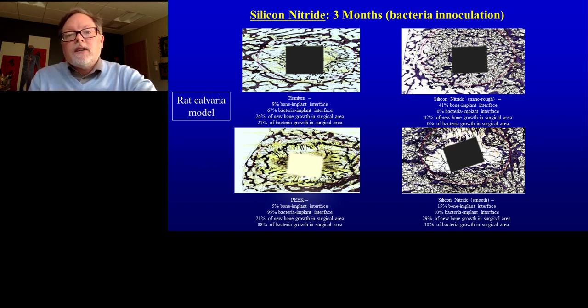No bacteria present on that surface after 3 months. That, of course, allowed for a lot more bone growth. In fact, the most bone growth out of these 4 samples, and it was at about 41% of that surface of silicon nitride was covered with bone.